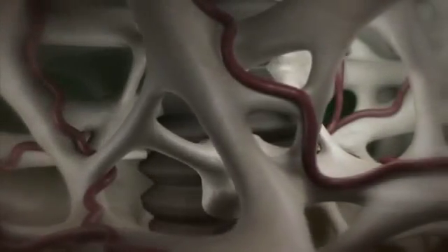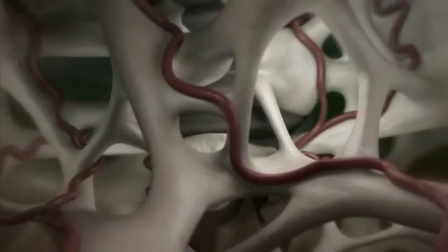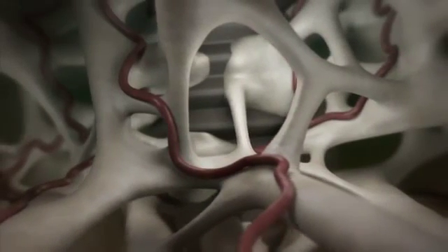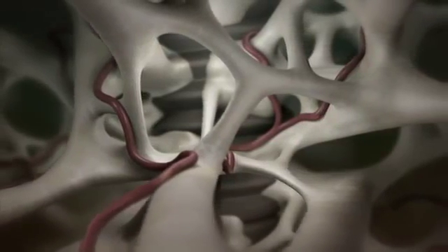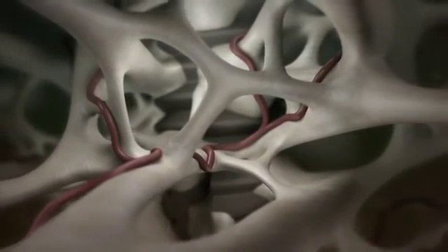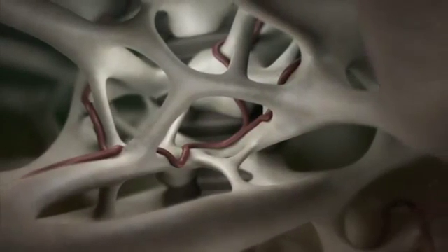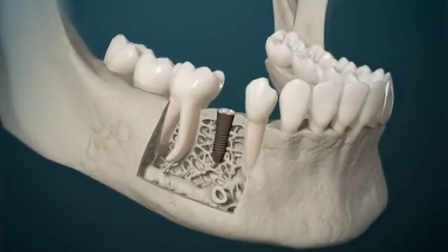At the end of the first week after surgery, woven bone is formed at the implant surface. This in turn promotes increasing secondary stabilization of the implant, making up for the progressive loss of primary stability. The formation of woven bone concludes the proliferative phase of wound healing. Orderly and coordinated bone remodeling restores the stability of the site.